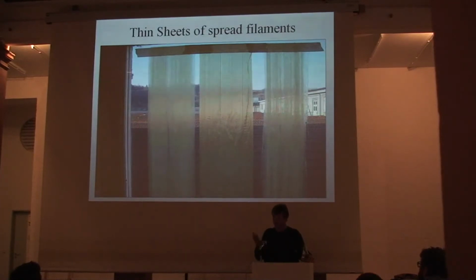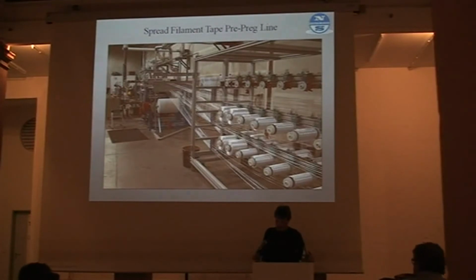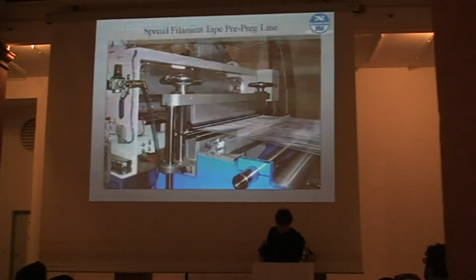And this is, in the composites world, known as a pre-preg tape, for pre-impregnation. So the filaments are pre-impregnated with resin. So the sort of traditional GRP or glass reinforced fiber composite that people think about, where everything is goopy and soaked with resin, is eliminated in this process because, again, it's a high modulus fiber, in this case with a lot of strength as well. So fiber comes in spools or bobbins like this. So we're pulling the fiber off the bobbin into this pre-impregnation head over here.